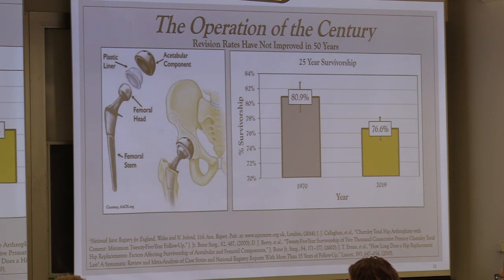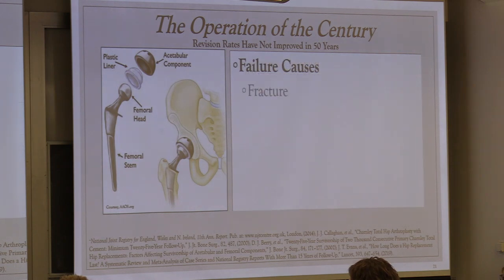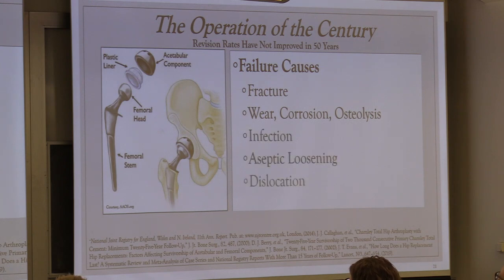Whereas today, or actually just a few years back, it's significantly lower than that. So isn't that a sad case of what's happening in the industry? I do think so. So why is that? Well, if you look at the reasons for failure, the failure causes are actually all the same as happened with John Charnley. They're fracture, wear, corrosion, osteolysis, which is death of the bone next to the implant, infection, and aseptic loosening, which often come together, and dislocation of the device.